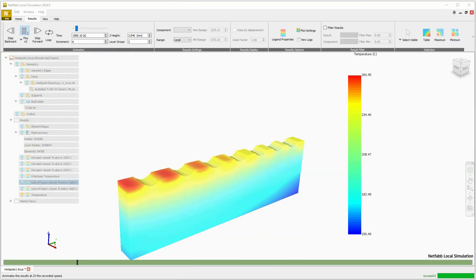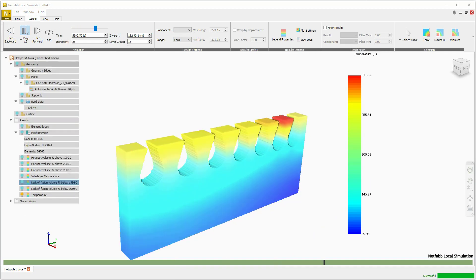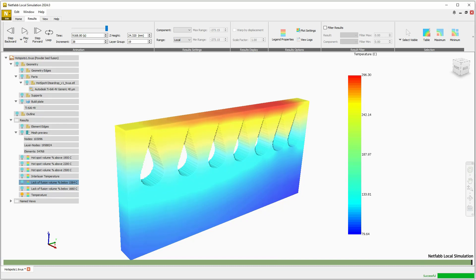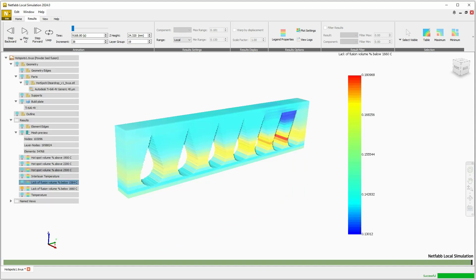The prediction of lack of fusion and hotspot failure modes has been dramatically improved in Netfabb Simulation. With the 2024 release, during the PRM generation process, the material conductivity at melting temperatures is enhanced to approximate the convective flow inside the melt pool.